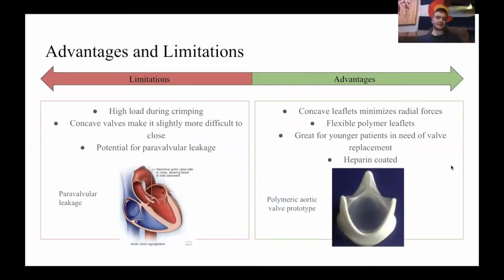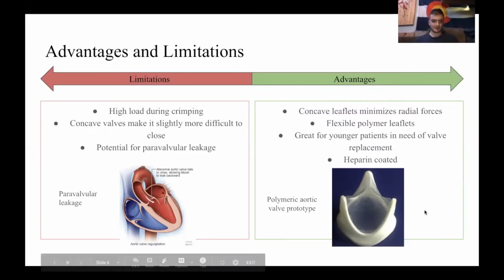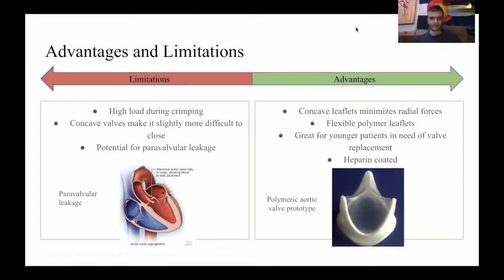So our device has advantages and limitations. To begin with the limitations, there's a high load during crimping. The concave valve shape makes it more difficult to close due to the blood pressure on the valve, and then there's potential for paravalvular leakage due to this. Some advantages are that the concave leaflets minimize radial forces, which is good. There are flexible polymer leaflets which provide the strength that a mechanical valve leaflet would with the compatibility of a bioprosthetic valve. And then they're great for younger patients in need of valve replacements because it's minimally invasive, and the heparin coating allows for no blood clotting to form.